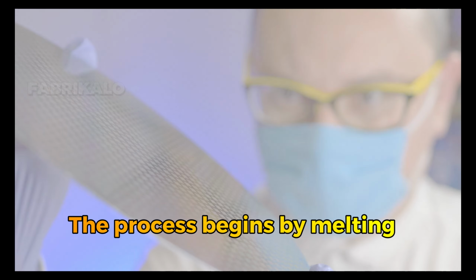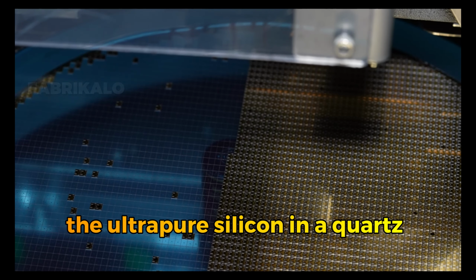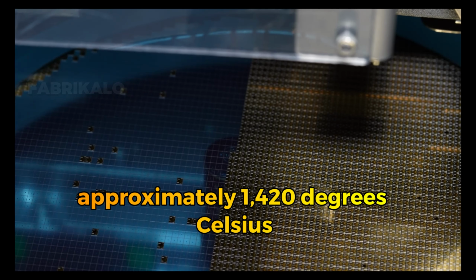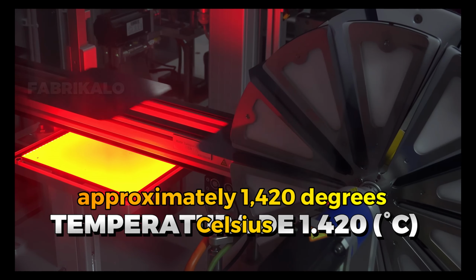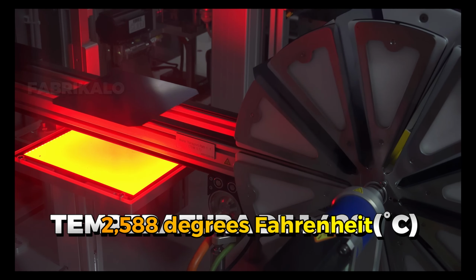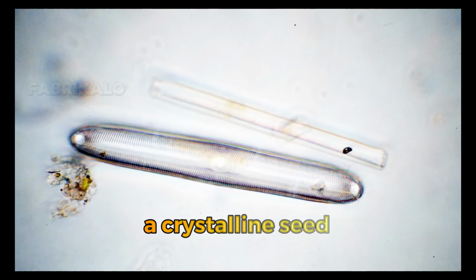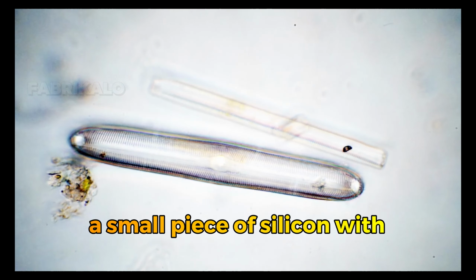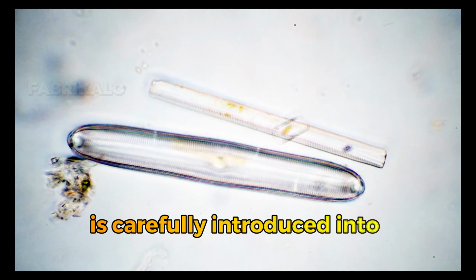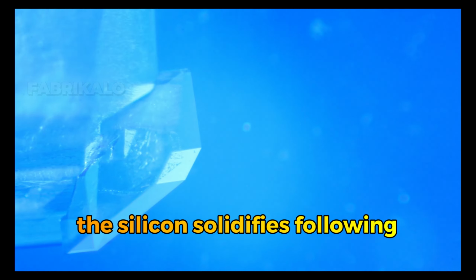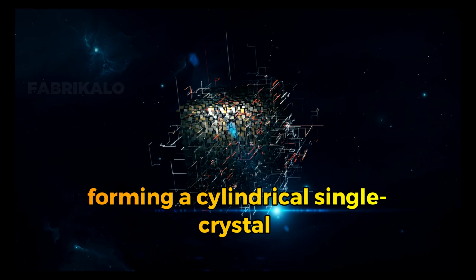The process begins by melting the ultrapure silicon in a quartz crucible at a temperature of approximately 1,420 degrees Celsius (2,588 degrees Fahrenheit). Then, a crystalline seed, a small piece of silicon with a defined crystal structure, is carefully introduced into the molten silicon. The seed is slowly rotated and pulled upward in a controlled manner while remaining in contact with the molten silicon. As it is drawn out, the silicon solidifies following the structural orientation of the seed, forming a cylindrical single crystal ingot.